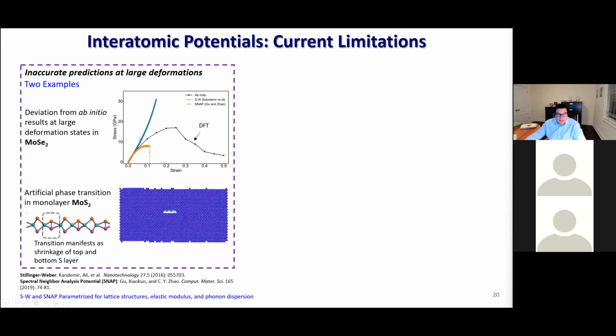And if you do the simulation with two force fields that you can find in the literature, one is Stillinger-Weber in this reference, and another is a machine learning force field that was parameterized looking at the environment of the atoms. It's called SNAP. This is what you see. So at large deformation, which is what's happening at the crack tip, you are very far off. And this is not surprising because these people were not studying fracture. They were studying thermal conductivity and many near equilibrium, small deformation properties like lattice structure, elastic modulus, phonon dispersion.